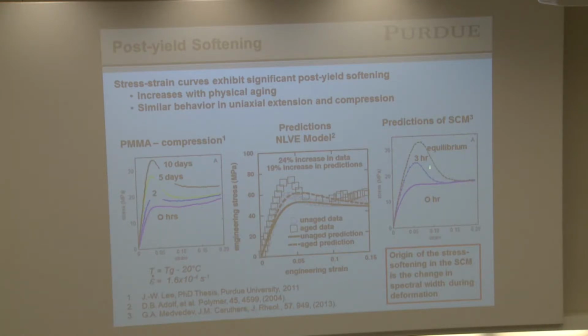This one here is what the stochastic model predicts. It predicts, in fact, that we have yield, we see this post-yield softening of the material, and we see it changes with aging time. So what it tells us is the model in its simplest form captures the right piece. And my view is getting simple models to capture the qualitative features is the first step before you start to worry about things.